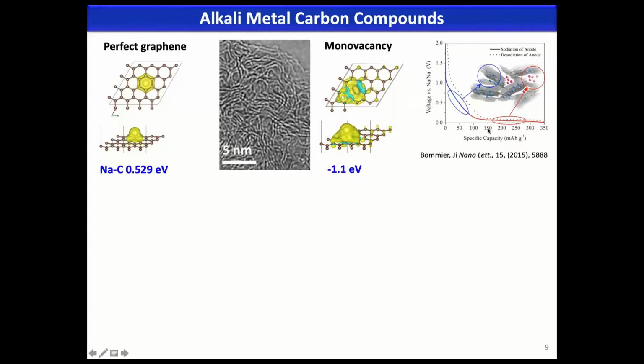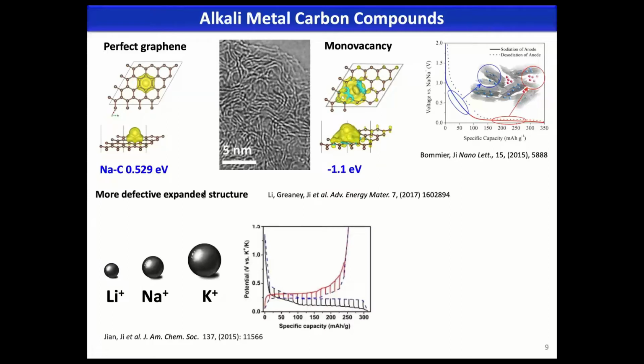And we have some studies on the mechanism for hard carbon in terms of storing sodium ions. And eventually, we derived a design principle for hard carbon, which is a more defective, expanded structure to have a bigger capacity for sodium ions. And size matters, but it's not always dominant. If you think about it, graphite cannot store sodium ions, but graphite can store potassium ions, and potassium ions are way bigger than sodium ions. So it's all about the entire thermodynamics, the Gibbs free energy for the reaction between the metal and the carbon structure, right? It's a simple reaction. If the Gibbs free energy is negative, you're going to have the intercalation.